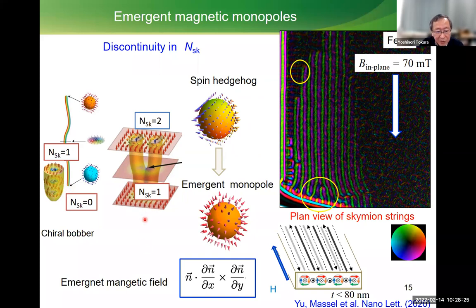Another way is if the skyrmion shows bifurcation, the skyrmion splits into two like this. Originally here we observe skyrmion charge one, and this is skyrmion charge two. Then there should be some discontinuity point defining the singularity, and this singularity point shows what we call the spin hedgehog-like structure. However, according to our famous relations to calculate the topological charge or winding number, we just convert this spin texture into the distribution of the emergent magnetic field. Then the emergent magnetic field shows a disk-like structure. It's nothing but the monopole structure. It looks like a source or a sink of the emergent magnetic field itself.